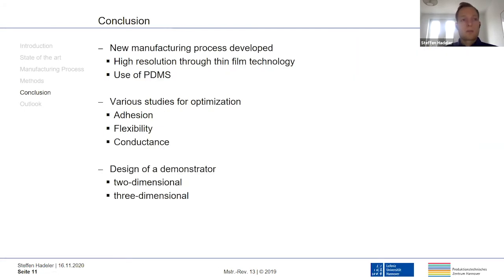Now I would like to come to a summary. In this work, a manufacturing process for the fast transfer of the conductive structures to PDMS using biocompatible materials was developed. I only use water-soluble transfer and the PVD process. Several investigations were carried out to improve the adhesion, the flexibility, or the conductance of the system. And finally, a demonstrator of an ECoG electrode array with 8 electrode contacts was built, and the transfer to three-dimensional shapes was shown as well.